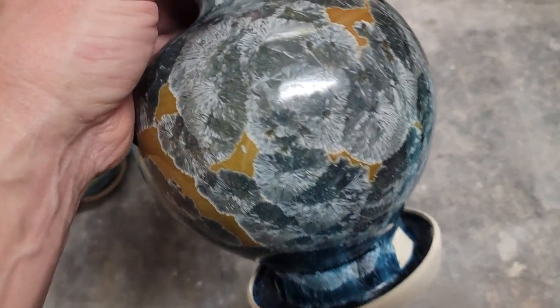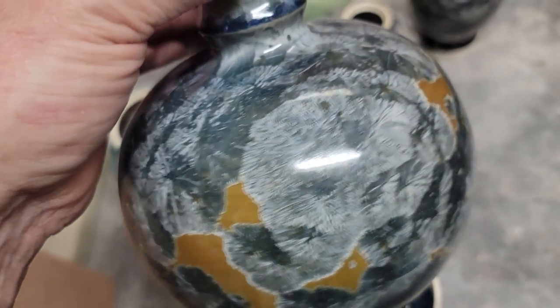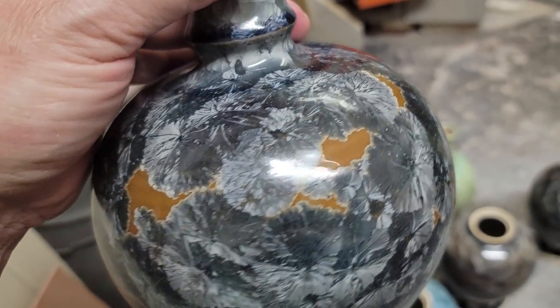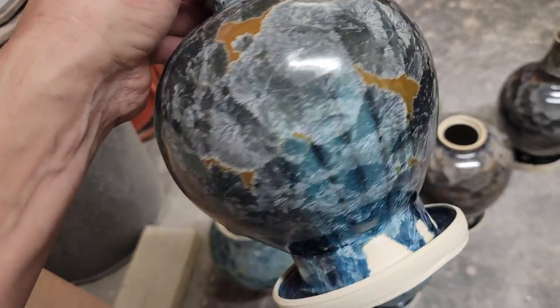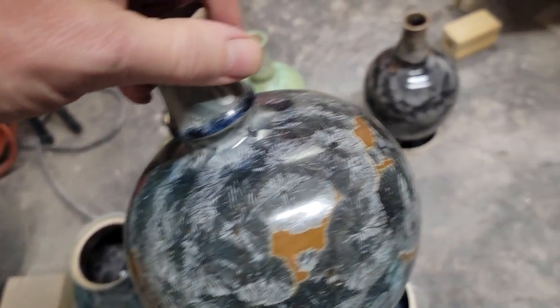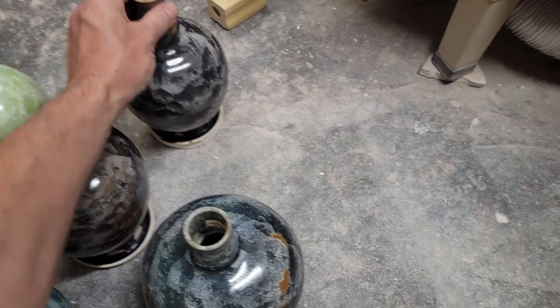This one has some field — this is a manganese-based glaze — and there's still a little crazing in there and it will continue to craze. We call this over-nucleated, which means a lot of the crystals didn't burn out before they started growing, so it just turns into this giant field of crystals.